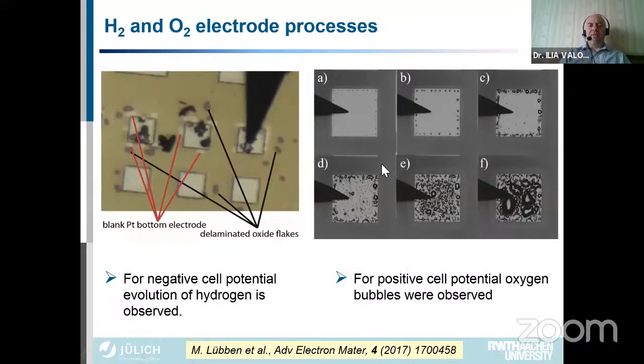And you can see such types of devices show this when you expose them to an extreme atmosphere. So it's about 90% humidity, just to accelerate the processes. You see that if you apply negative voltage, you form hydrogen, which is characterized by some kind of explosion from the bottom of the device. If you apply positive voltage to the electrode, you see with time how oxygen starts to form. It starts to form from the edges because the current density there is the highest. But when you cycle more and more cycles, you see the whole area is covered by oxygen.